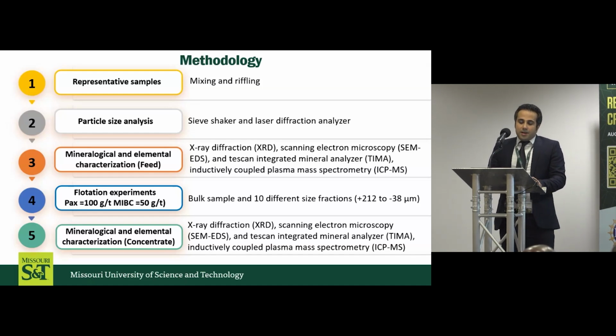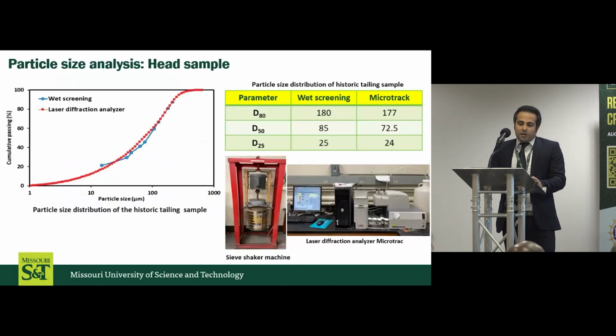Mineralogical analysis showed that pyrite is the main host of tellurium and critical elements. Therefore, we conducted flotation experiments based on the recovery of pyrite. Finally, mineralogical analysis was done to identify tellurium-bearing minerals, their abundance, and their liberation in the concentrate. The particle size analysis showed that 80% and 50% of the head sample are finer than 180 and 85 micron, and nearly 25% of the head sample is smaller than 25 micron.